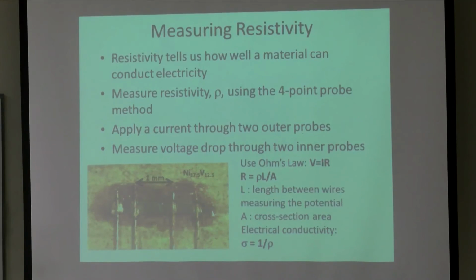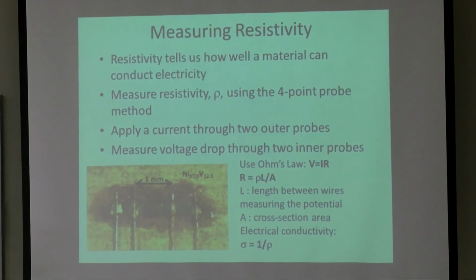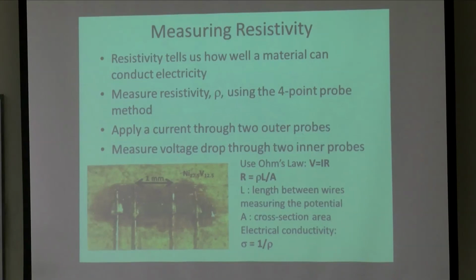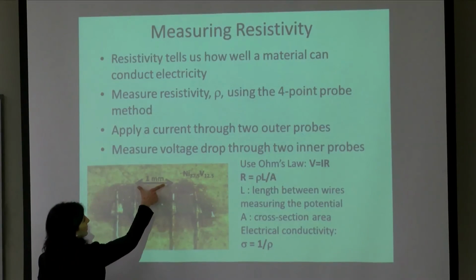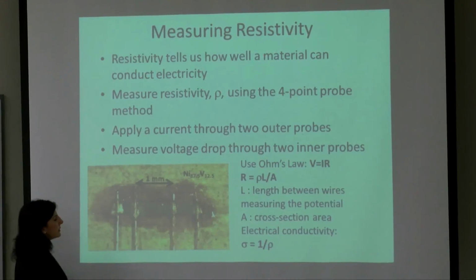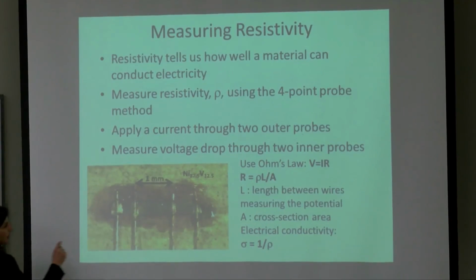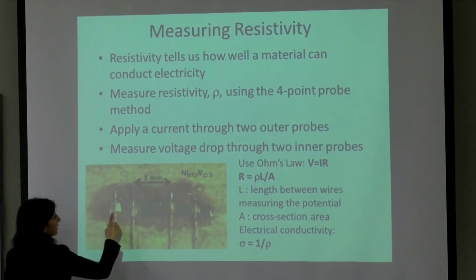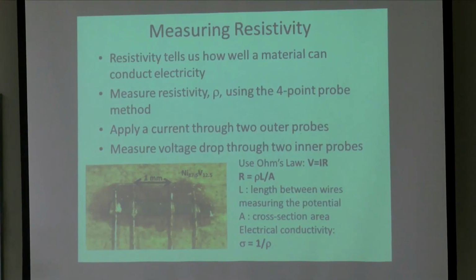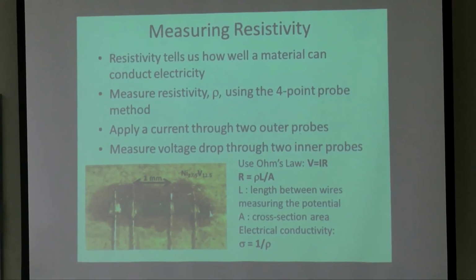This is just something I threw in because this is a very quick technique to measure resistivity. So this is an electrical measurement, the 4-probe method. This is, again, a nickel vanadium sample. The distance here is about 1 millimeter, so you can imagine how tiny this is. And you had to coat these all by hand using silver epoxy. The idea is that you're able to get the electrical conductivity of a material this way.